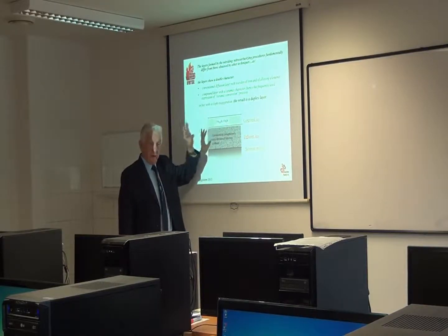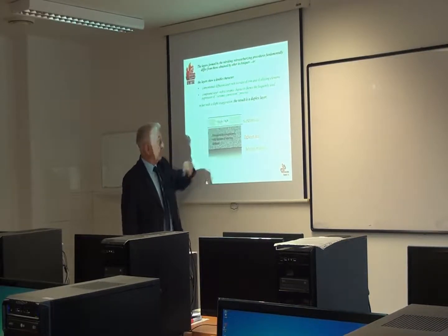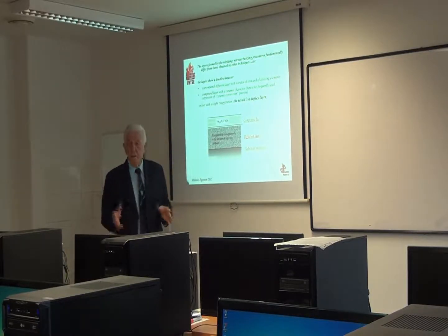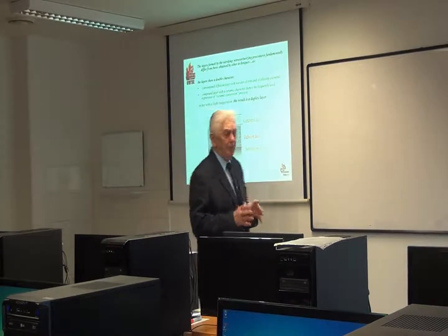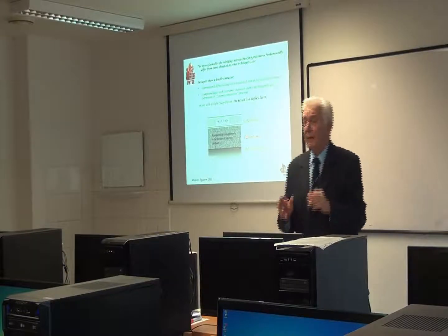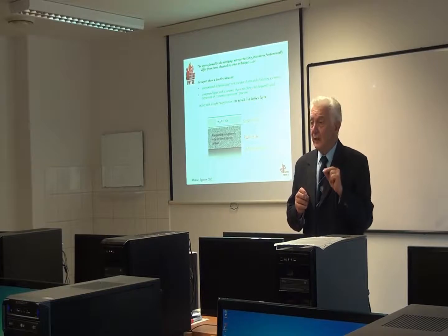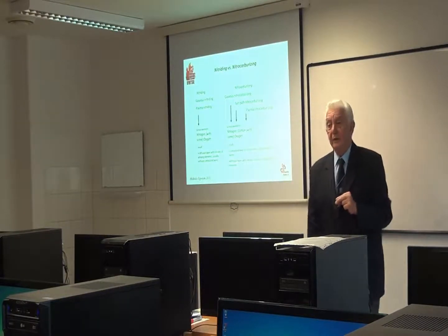We will talk about these layers a little bit more, but basically we have to know that a nitrided surface is always composed of these two parts, the compound layer and the diffusion layer to the substrate material. Certainly they have different properties, the compound layer and the diffusion layer. But this kind of dual structure of the surface is extremely important when we consider the application field of nitriding.